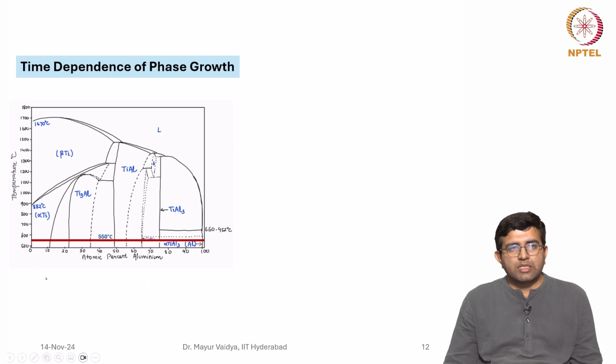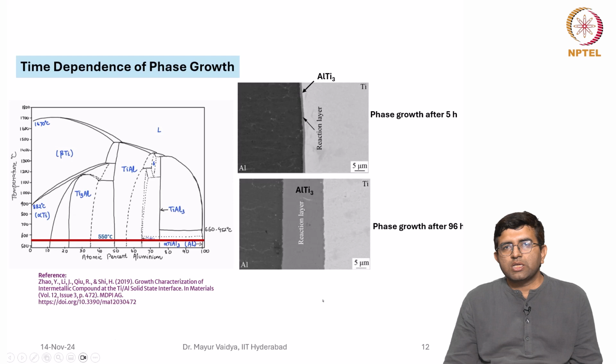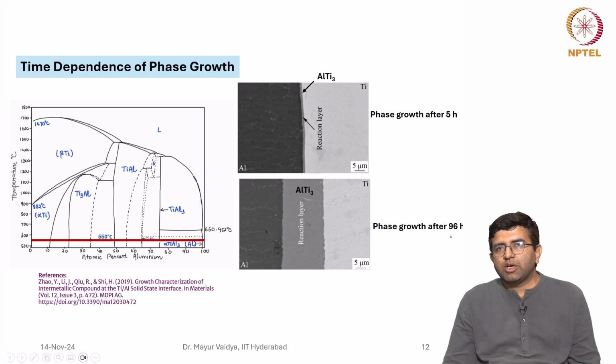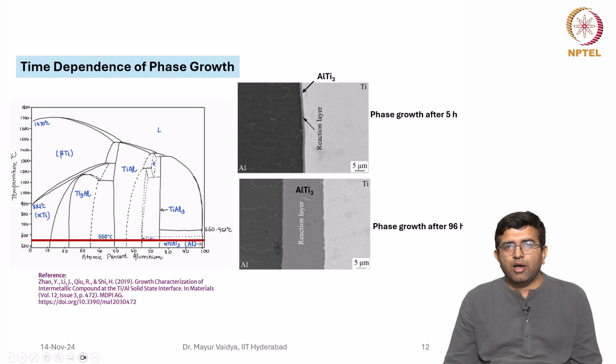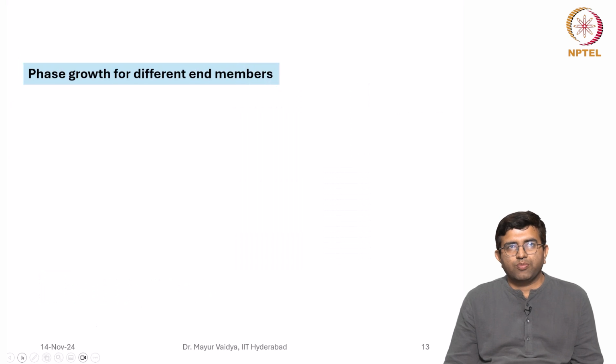Another instance is the same Ti-Al that was shown previously. You see here the thickness of the Ti3Al layer after 5 hours versus the thickness after 96 hours. This is significantly higher. So time is therefore another important factor which influences the phase growth.